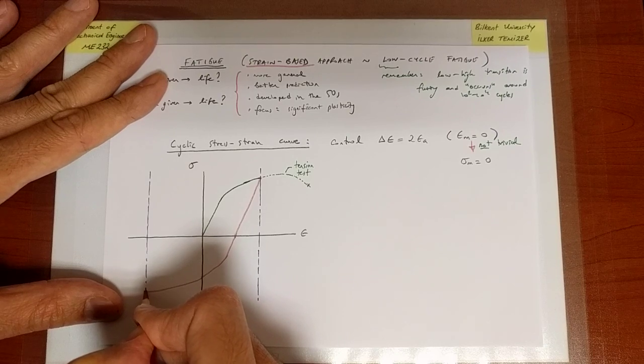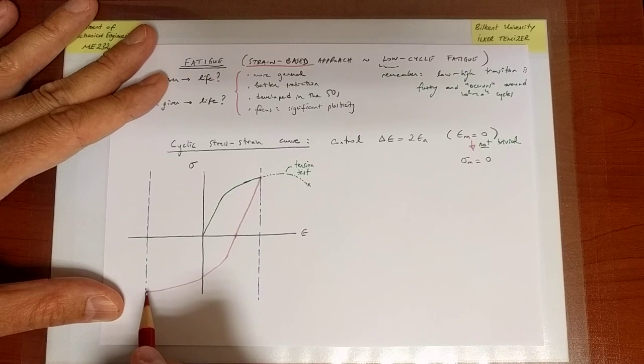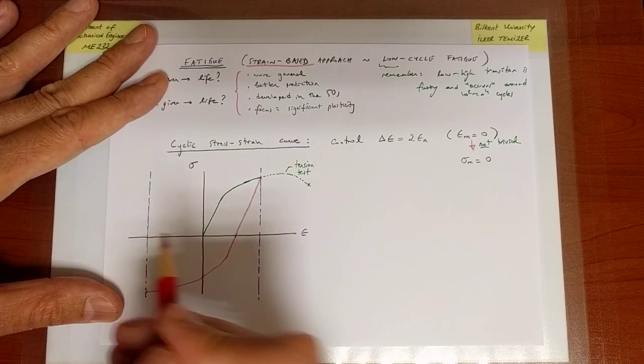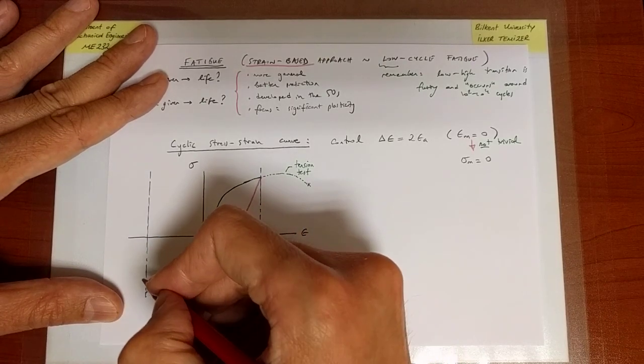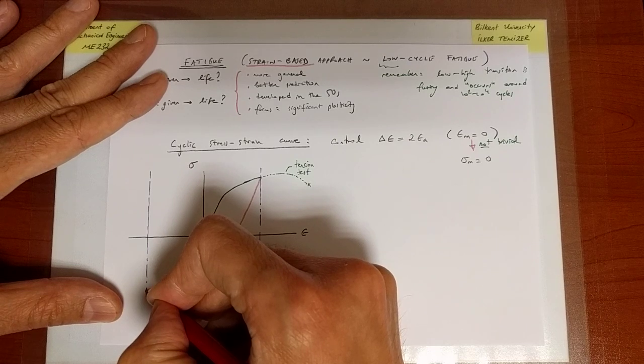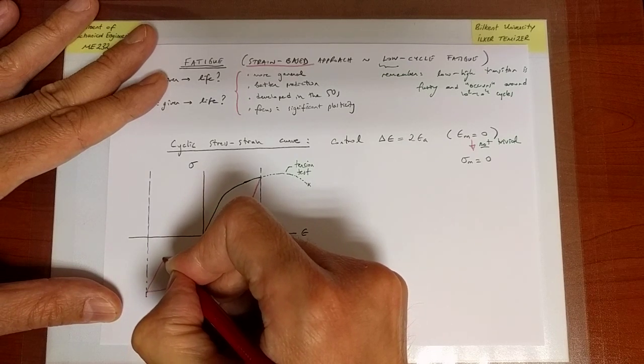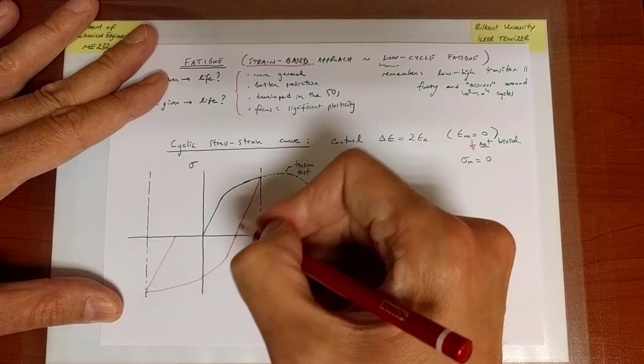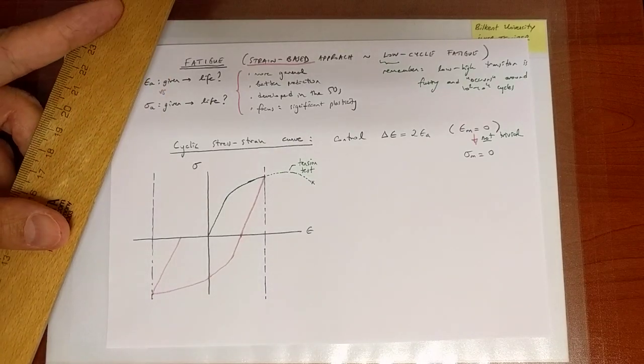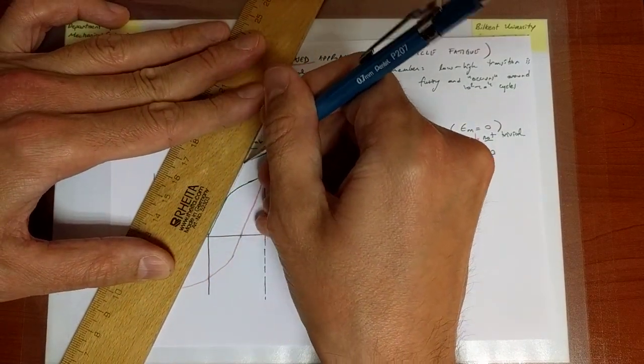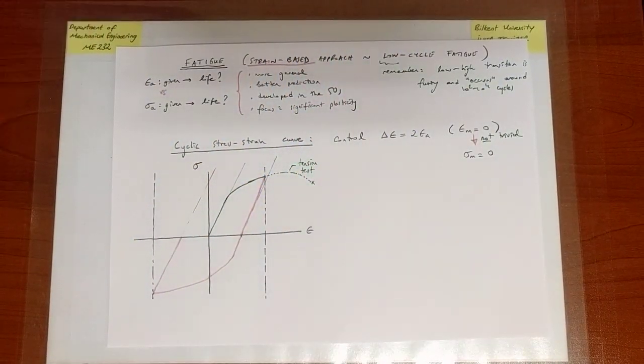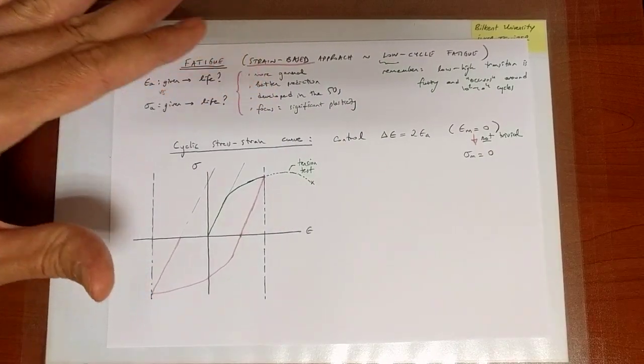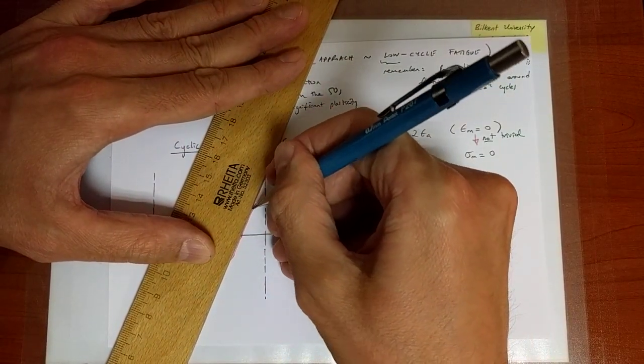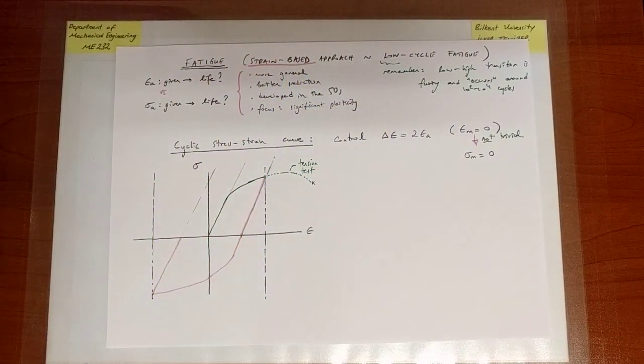And then we go to a certain value, to the minimum strain. When we hit that point, of course, we could have gone until something like failure perhaps happens, but we're going to stop and load back. When we start to remove the load towards zero, again it turns out that this behavior is elastic. In other words, I proceed on a line that is parallel almost to the initial line. So this is one line, this is another line, that's another line, and all of those lines are almost parallel to one another. Let me correct this a little bit. It's not exactly a nice parallel line, so let's do it like this. Okay. So all of those have slope almost Young's modulus.